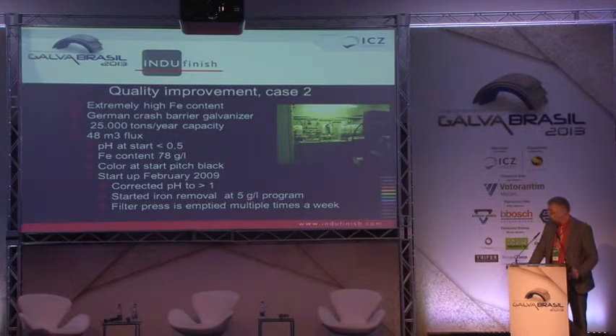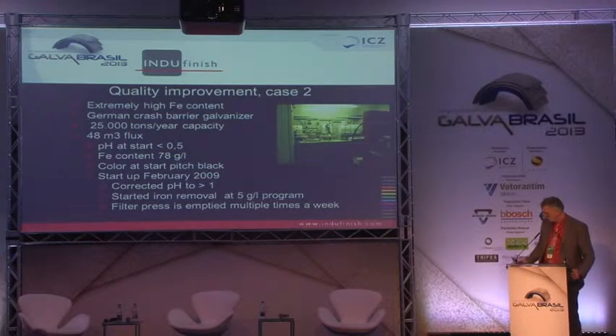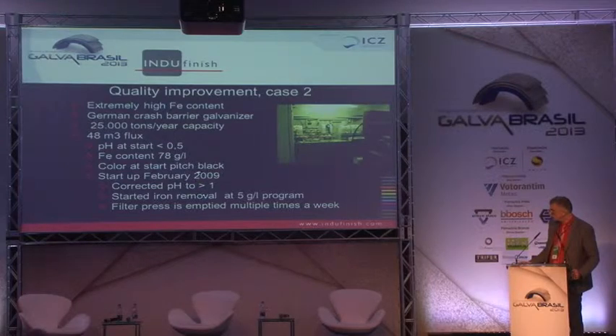But in the end, we sold the unit, we installed it, we started in February 2009. The pH was below 0.5, but actually we couldn't measure it. If the pH is that low, you can't oxidize iron. So we moved up with the pH, and we wrote a different program, 5 grams a liter, otherwise it would take more than a year. And they had to empty the filter press multiple times a week.